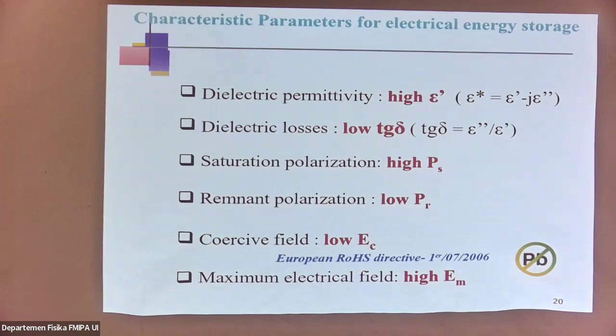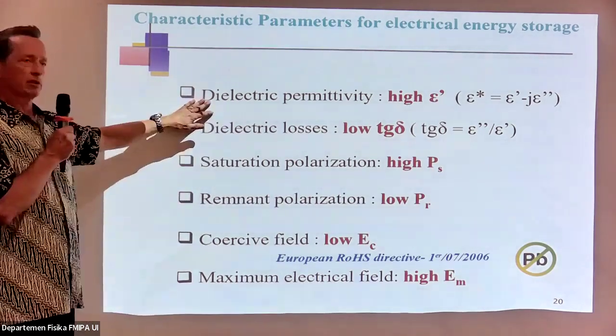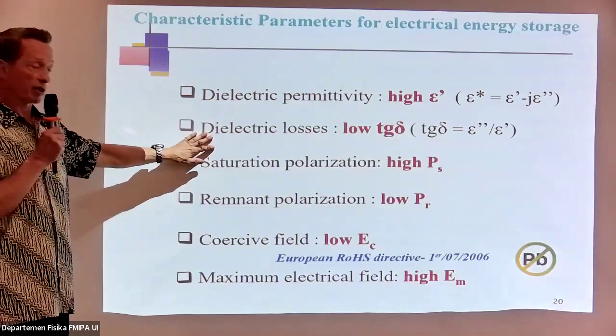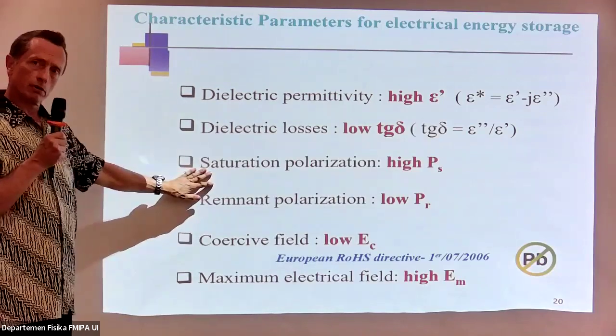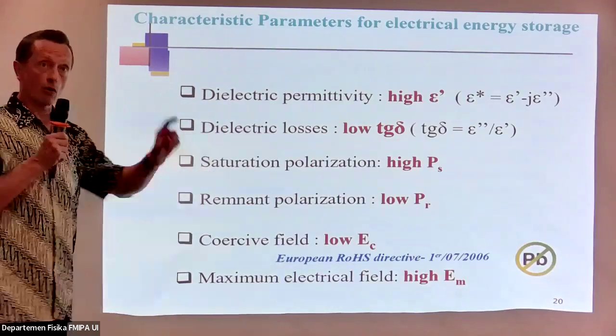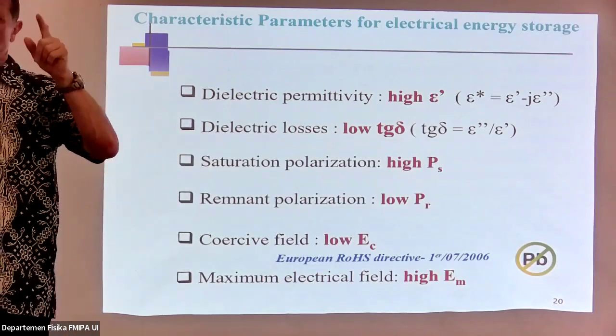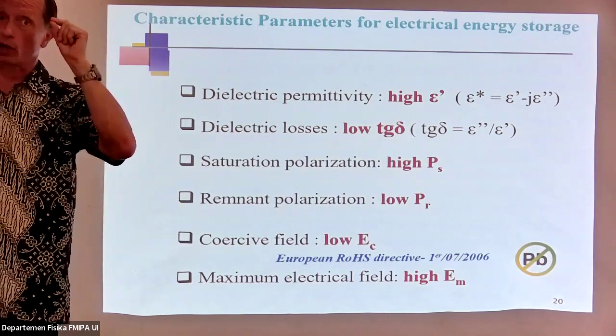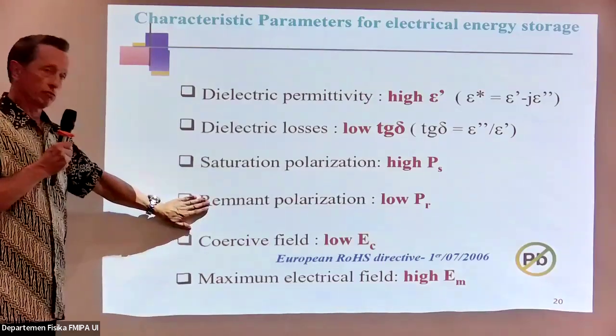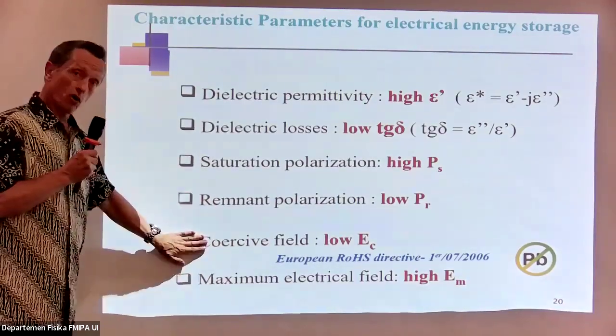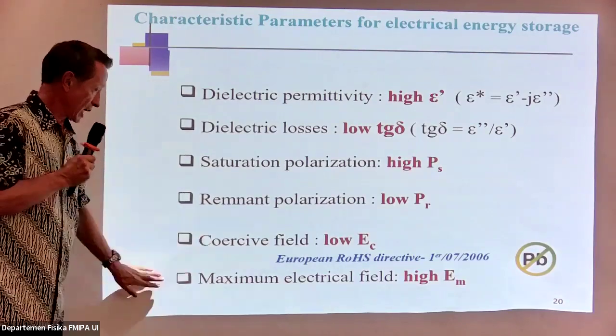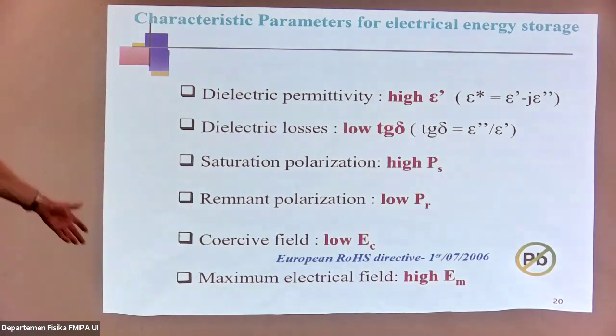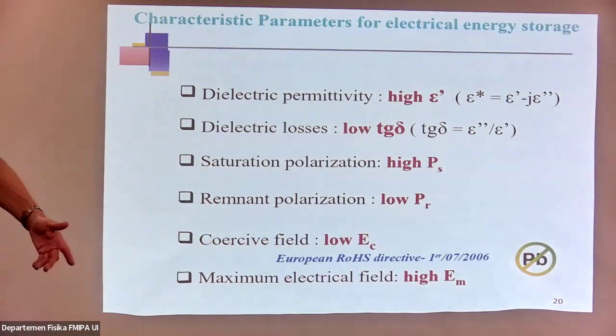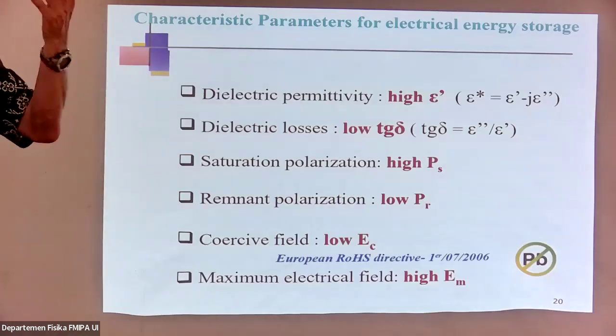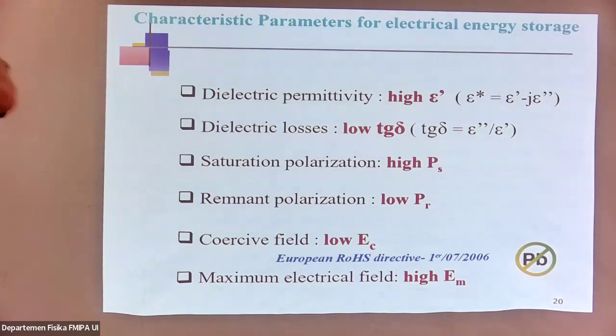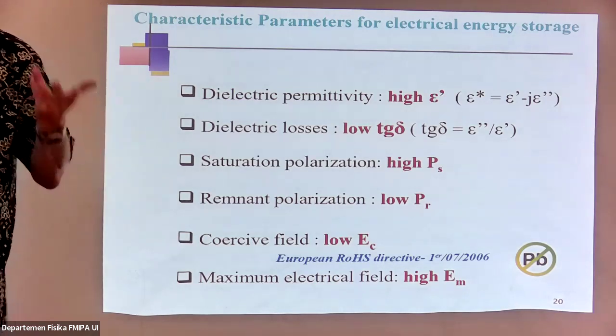So these are the parameters you need for electrical energy storage: high electric permittivity, low dielectric losses, high saturation polarization. So I repeat, high saturation with very low remnant polarization, very low coercive field, and then a high maximum electric field, because the possibility to store depends on the possibility to increase the voltage applied to the material and then to the device.